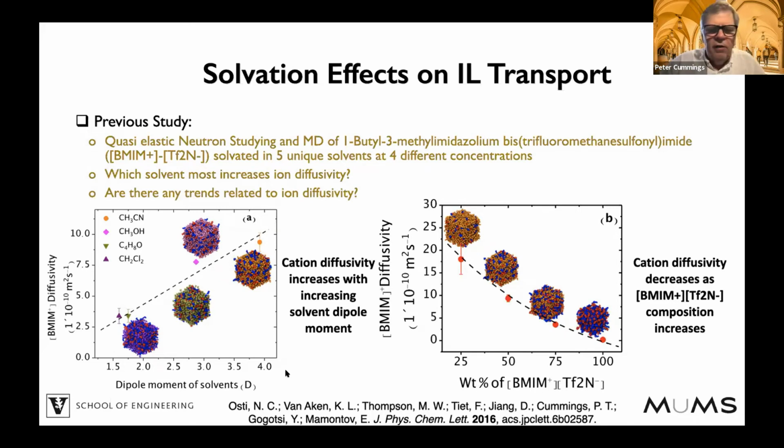We were able to motivate that from the point of view of a higher dipole moment of the solvent: the better dielectric screening there is of the ion-ion interaction, and therefore there would be less ion-ion pairing in higher dipole moment systems.